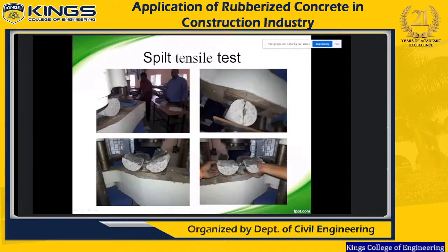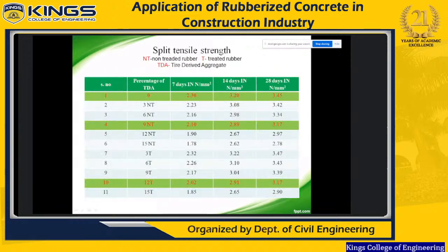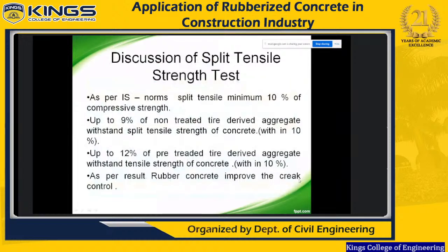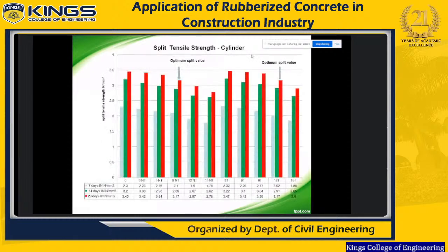The split tensile strength was carried out in our laboratory. Based on this ratio, we obtained the split tensile strength. 9% of non-treated rubber gives the optimum value, as well as 12% of treated rubber. As per the result, rubber concrete improves crack control. We are aware that rubber is somewhat elastic in nature, so it is also good for that. This is the split tensile strength of the cylinder, with the optimum at 9% and 12%.